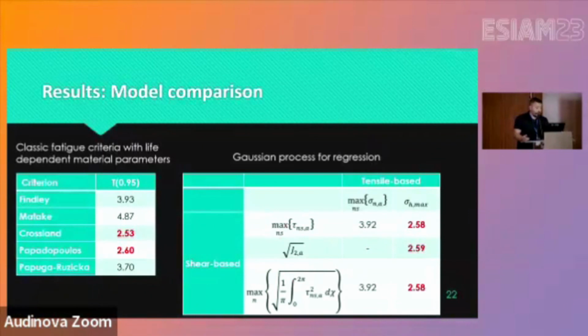You can see it in this table when the average scatter for Crossland and Papadopoulos is 2.5, 2.6. Same for our model. It's much worse when there are maximum shear and normal stresses. It's 4, but when there was a hydrostatic stress, 2.58, 2.59, as you can see here. It was surprising that we didn't have to train it on the multi-axial. And now we know it was just this one case, because this steel has very little to no plasticity, even in the fatigue life it was non-existent. So it was much easier for the model to learn. When we use other steels and aluminum alloys later, it's not shown here, we had to train it on the multi-axial, just to clarify.